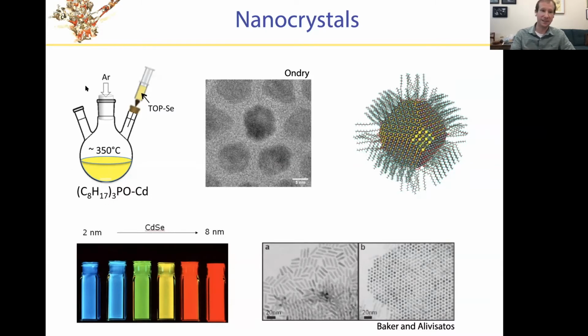It looks really easy in a schematic diagram. It's a matter of heating things up a little, injecting the component ions as well as a surfactant. That surfactant plays the important role of keeping these growing crystals from binding to one another and sintering, of defining their size. And indeed, what's formed is not just a random aggregate of those ions, but a nicely ordered crystal, as is revealed by high resolution electron micrographs of these systems, like the one shown here.